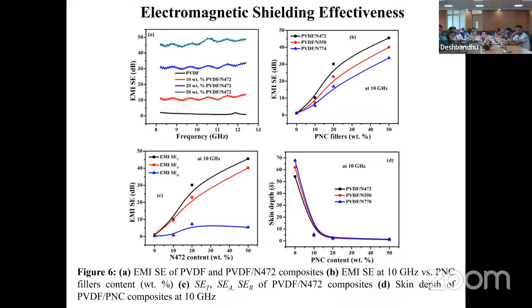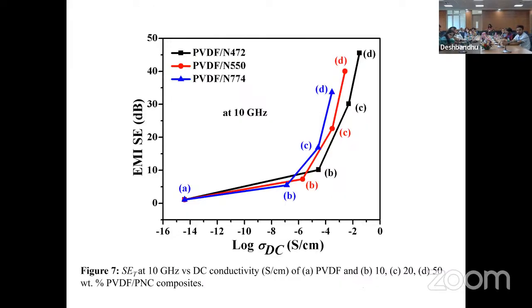And here I have also seen the 50% N472 effects in PVDF. In the second figure, what I observed is you can see the N472 is having the higher EMI shielding in comparison to other fillers at 10 gigahertz frequency. And EMI shielding of N472 at 10 gigahertz is also shown in terms of absorption, reflection, and total EMI shielding. Total EMI shielding is even higher than 40 dB. Okay, so these are the EMI shielding effects.